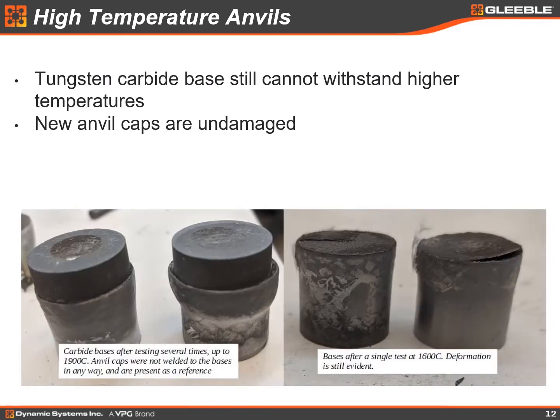Each test was followed by careful examination of the anvil caps for cracking, indentation, any sort of thermal breakdown, and they looked frankly perfect even after multiple tests at very high temperatures. However, after the final tests, it was noticed that the anvil bases themselves had been deforming. The tungsten carbide anvil bases were still getting much too hot for them to perform well.